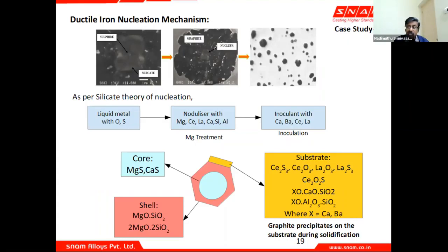This is the reason why we say you need some oxygen and sulfur in your base metal. No one prefers 0% sulfur in a base metal for ductile iron. You need some amount of sulfur and oxygen. Now on this, the substrates of cerium sulfide, cerium oxide, lanthanum sulfide, and calcium oxide, SiO2, aluminum oxide, SiO2, these calcium, barium, aluminum substrates sit on the shell and core. This is very, very important because this substrate is needed for graphite to precipitate.